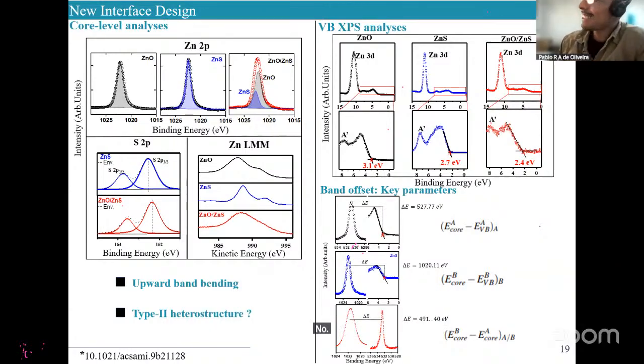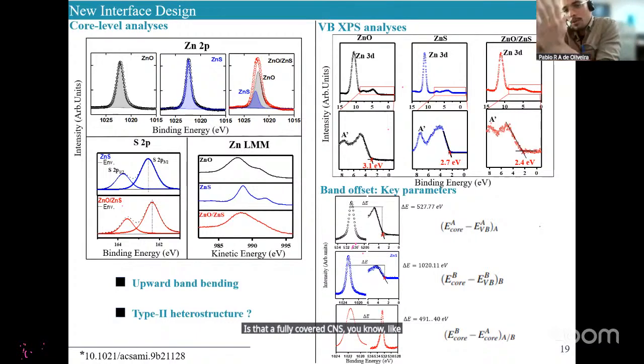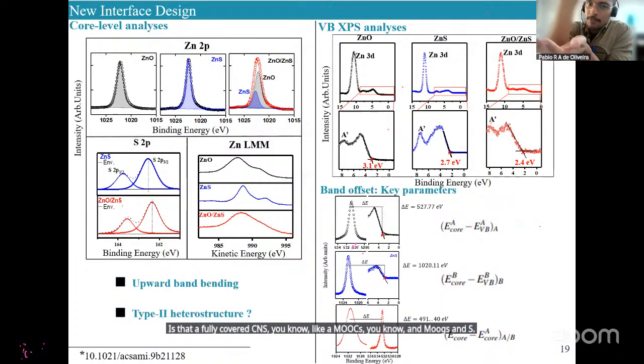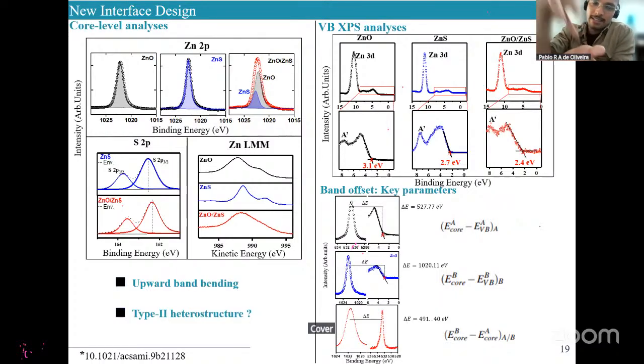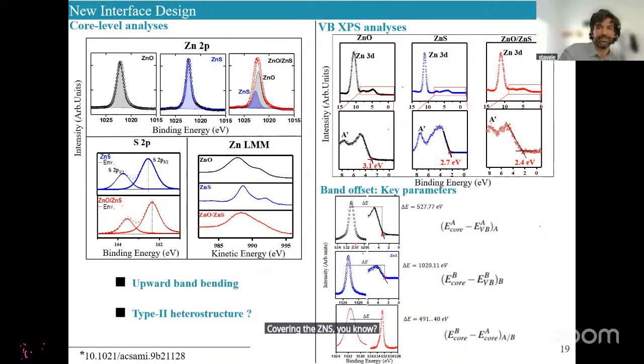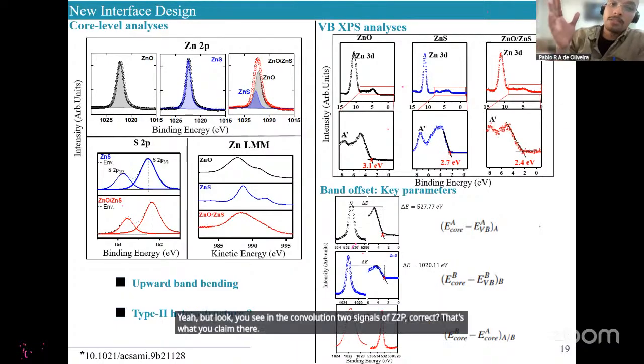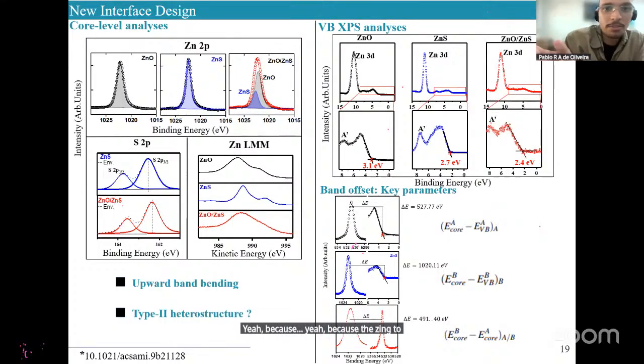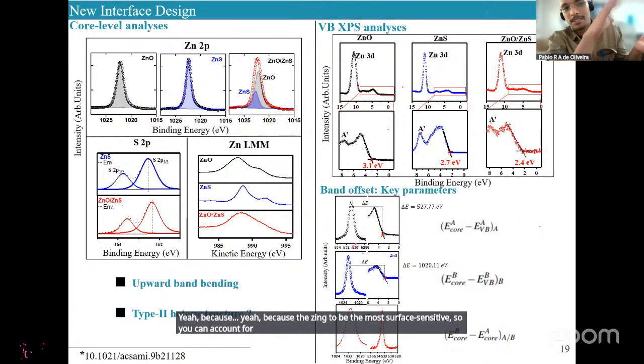No. With your data, you can. Effectively, this is the oxidized ZnS surface. It's not a fully covered ZnS, like a bulk ZnO and bulk ZnS. It's like a few layers of ZnO covering the ZnS. Yeah, but look, you see in the deconvolution two signals of zinc 2p, correct? That's what you claim there, because the zinc 2p is the most surface sensitive, so you can account for the contribution from the top surface.